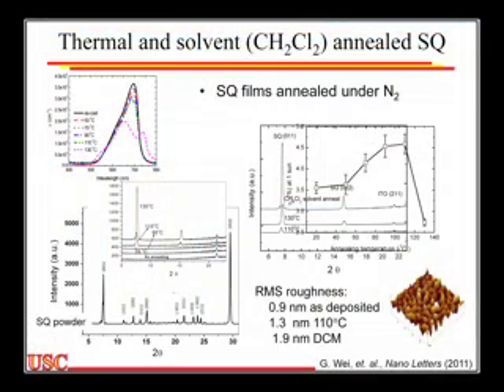So what happens if we anneal it? Well, the powder spectrum is shown here, and I just realized this morning that's not indexed correctly. This is an older slide. That's indexed correctly. This is indexed wrong. But the key is we have the single crystal structure that I'll show you in a few minutes. But if we start with the film, you can see that there's the trace here. There's no annealing, and there's nothing to see. We go to 70 degrees, there's nothing. 90 degrees, there's nothing. When we get to 110, we start seeing a peak grow in.